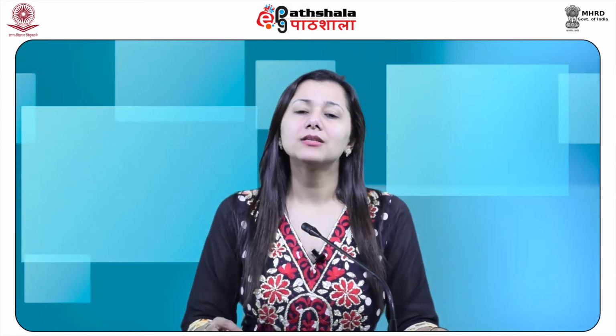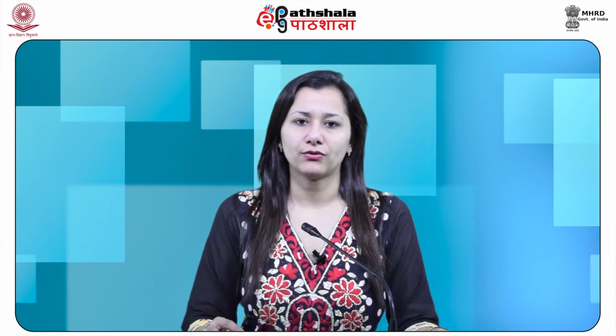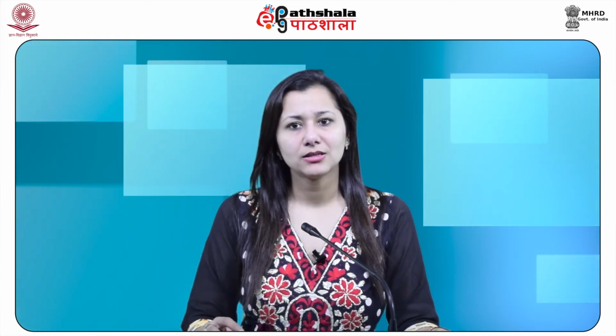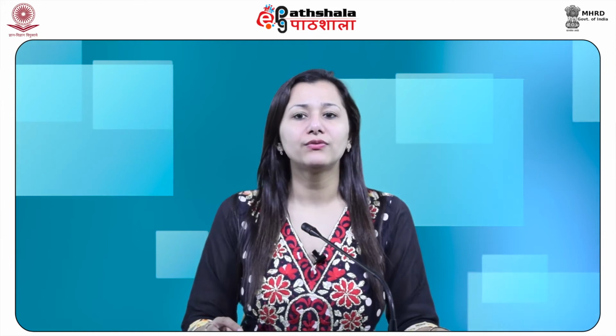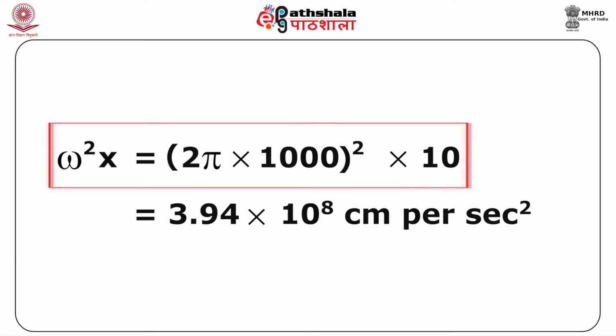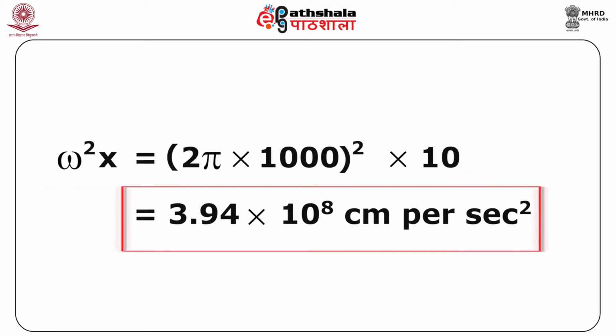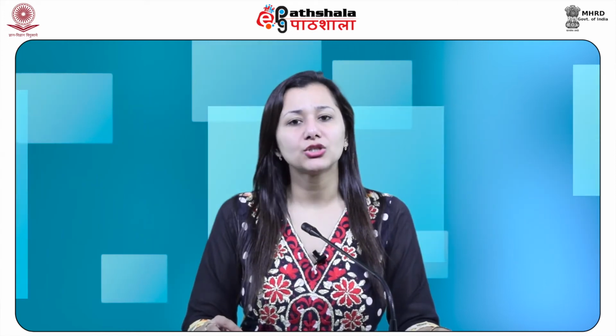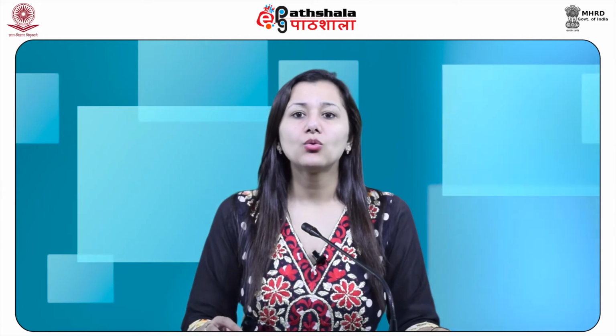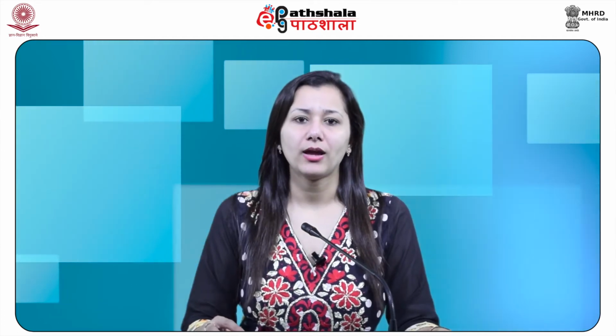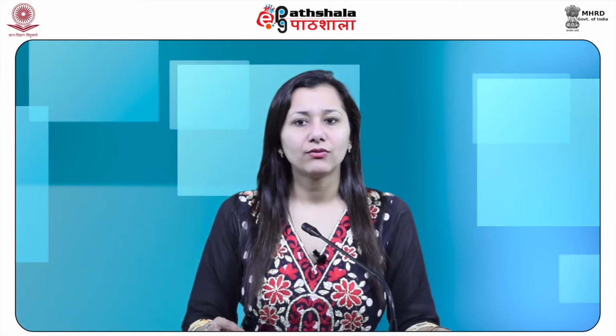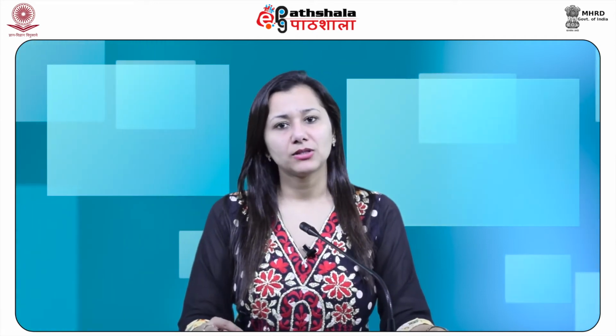If the particle is at a distance of 10 cm from the axis of rotation, that is x equals 10 cm, the acceleration in the centrifugal field would be equal to omega square x, which is equal to (2 pi times 1000) whole square times 10, equals 3.94 times 10 to the power 8 centimeter per second square. This is nearly 4 lakh times greater than the acceleration due to normal gravity, which is only 981 centimeter per second square. The rate of sedimentation therefore can be raised by 4 lakh times the normal rate.